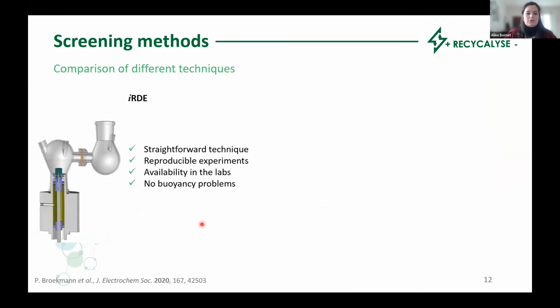So as a first short conclusion, we could see that by inverting the traditional RDE by 180 degrees, the bubbles are no longer an issue for our OER measurements. We finally have a setup for testing the performance of OER catalysts in a quick and reliable way in the labs. In Recycalyse, we want to move a step forward in the testing of the catalyst.